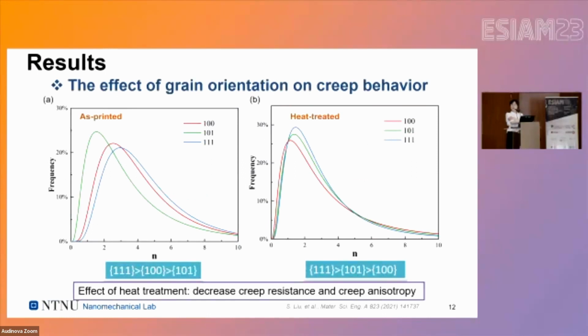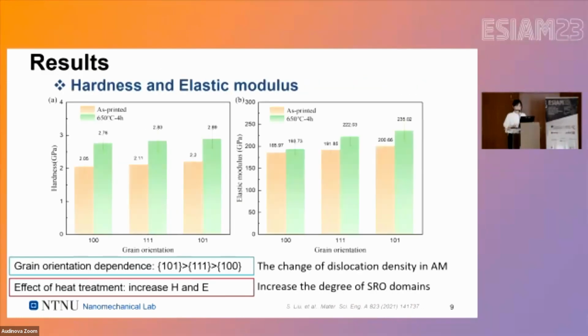Yes. That's because nanoindentation has a very small deformation volume, so the dislocation density in different regions might vary a lot. The results would be influenced by microstructure properties like the dislocation density and some precipitations in the microstructure. That might be the reason for it. But from our results, we can analyze the mean value and the trend, to study the difference between different samples or different orientations, to have an overview of the mechanical properties and see the tendency or the effects.